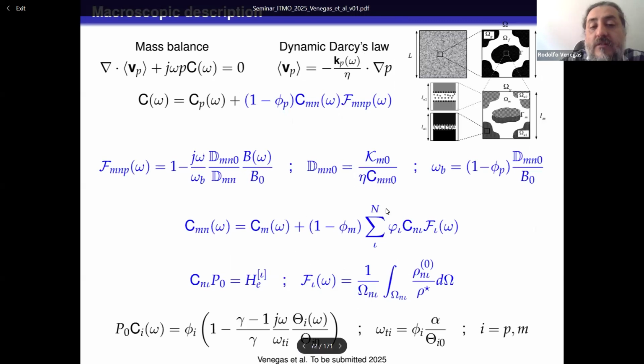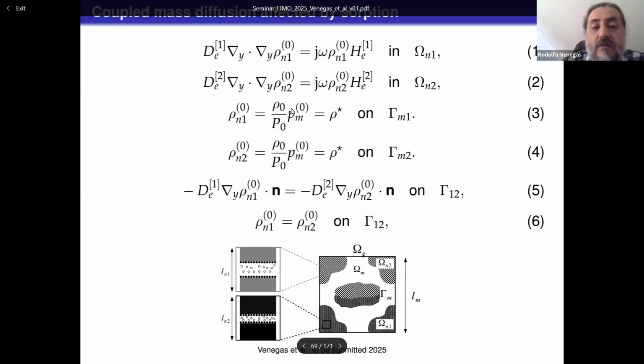In blue is what is different, but the difference is that a summation appears here, accounting for what's happening in these nanoporous patches. And this F function is defined in a very similar way to previously, but from the solution of this coupled problem instead of just a single mass diffusion equation that governs the problem.